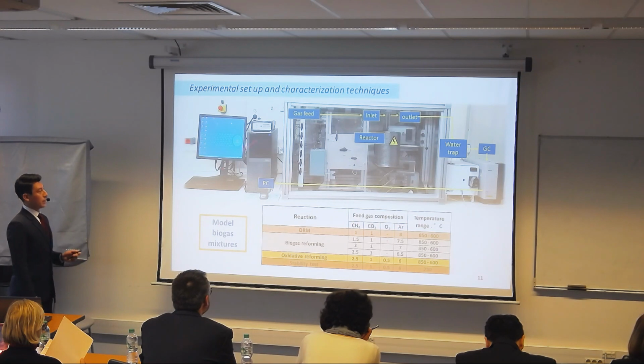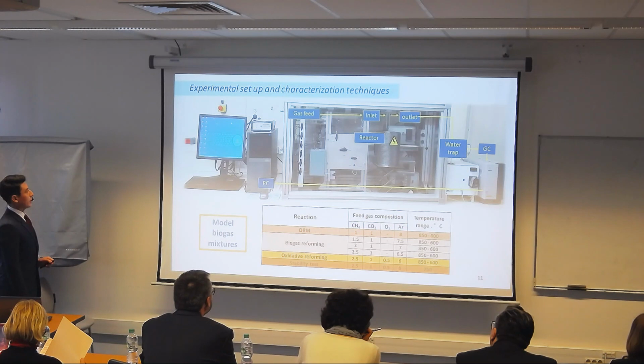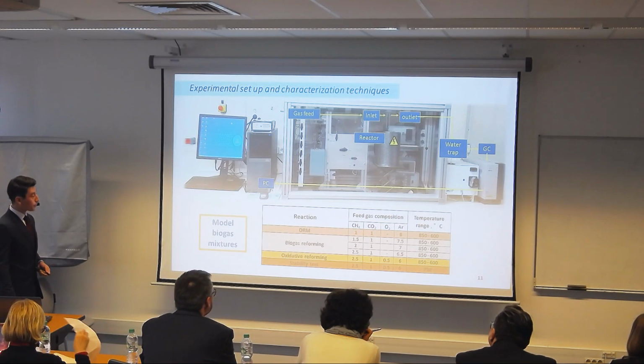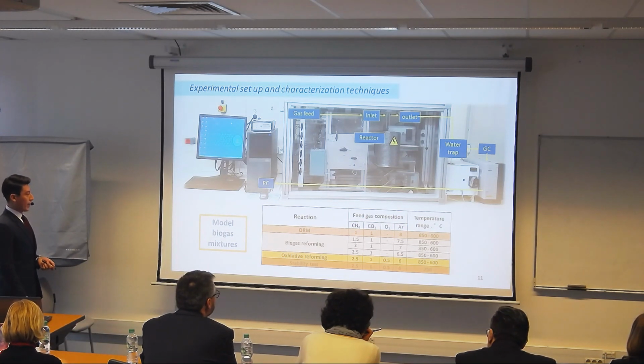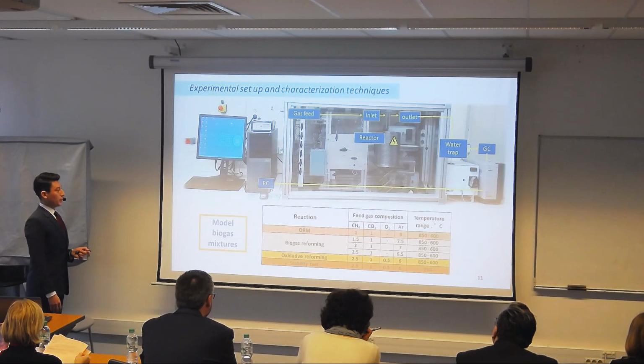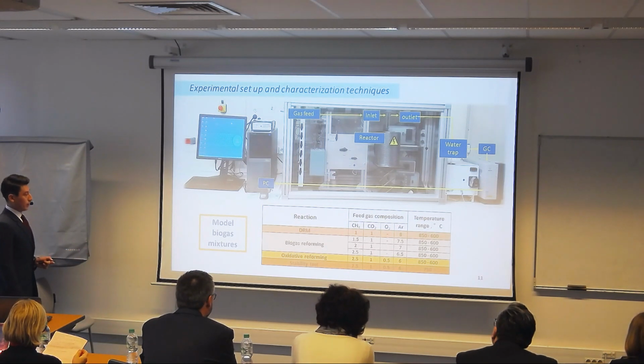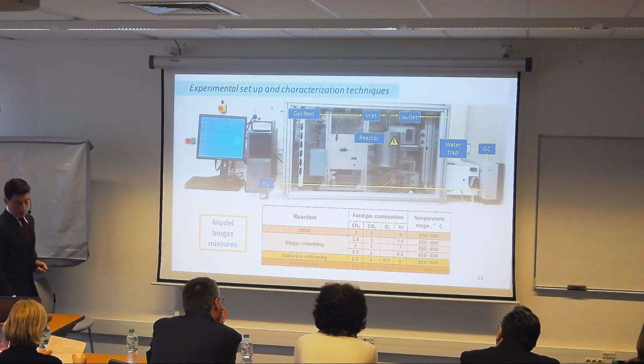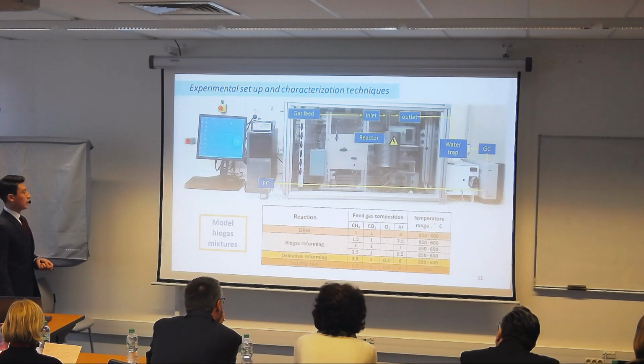You can see here in a general way the experimental setup that we have in the laboratory. Coming from the thermodynamic equilibrium calculation, we are going to start testing the dry reforming of this sample, the increase of methane in the biogas reforming, and also the effect of oxidative reforming, to see if indeed we have a decrease of carbon deposition. And for the stability test, we set the temperature up to 750 degrees.